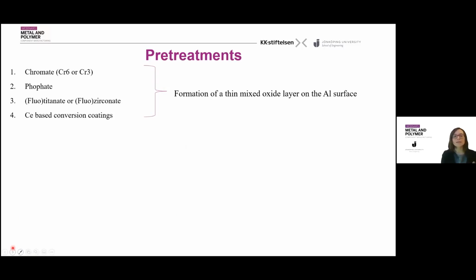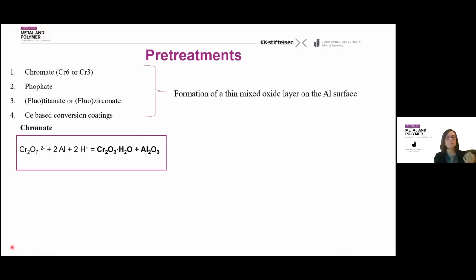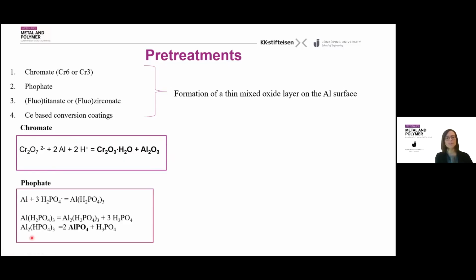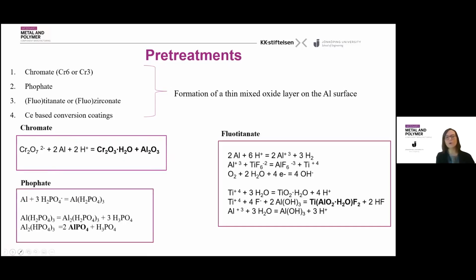Most of them work by formation of a thin mixed oxide layer at the aluminum surface. Chromate, for example, we have a chromate solution in which we immerse the aluminum, and they react chemically together, corroding a little bit the aluminum and forming a mixed oxide containing both chromium oxide and aluminum oxide. In other cases, the chemistry is more complex, with many more chemical reactions involved. But what you have to see is that at the very end, what we obtain is actually more or less the same: a mixed oxide layer containing aluminum and the main chemical ingredients that the pretreatment is based on, so aluminum phosphates or aluminum titanate oxides.